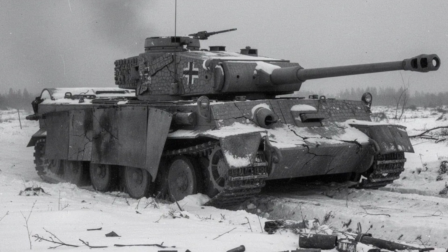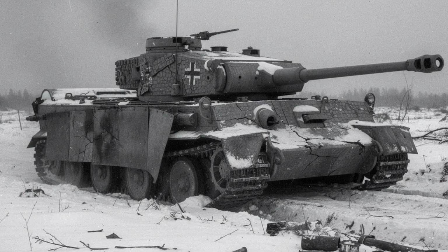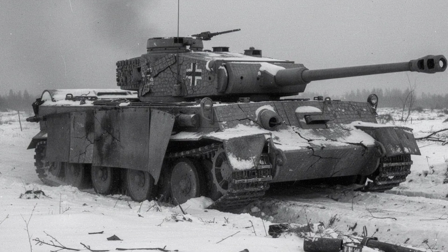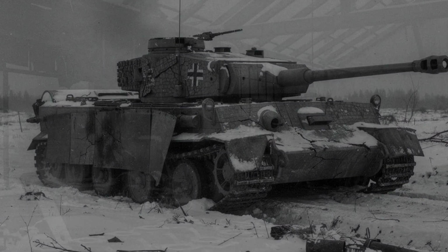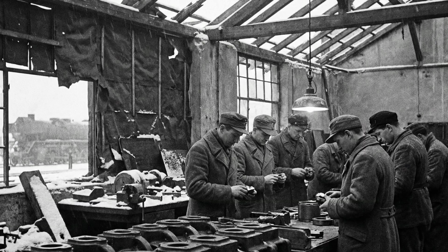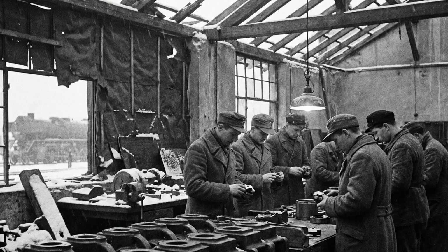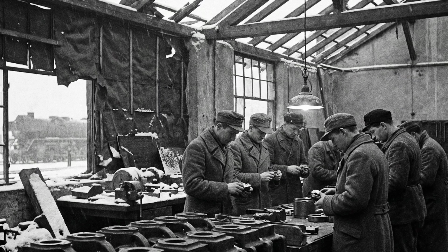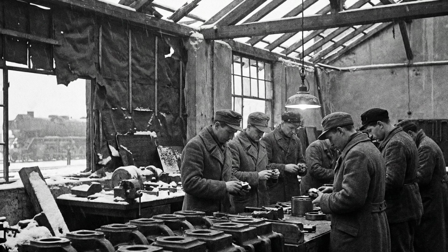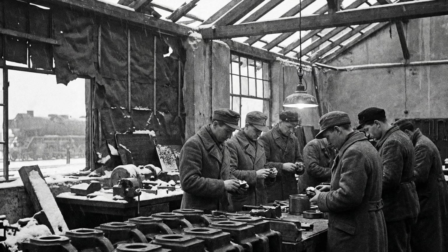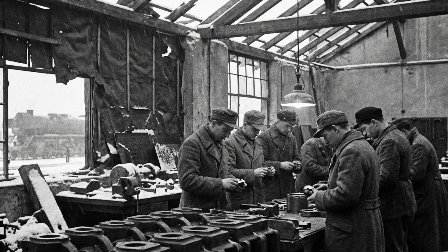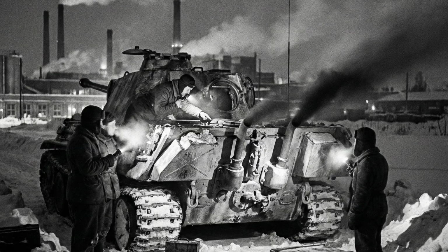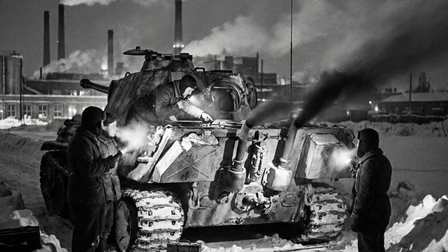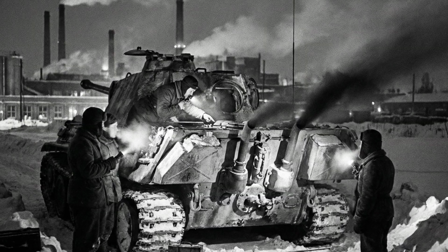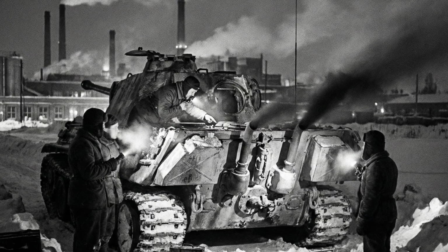Panther complexity. Inside the Panther program, the pressure was constant because the machine itself was complex. The Panther demanded roughly twice the machining hours of the older Panzer IV, about 1,500 hours versus around 800 in early runs. Its armor layout used interlocked plates and long weld seams that saved weight and improved ballistics, but added labor. Its 75mm KwK 42 gun offered long reach and high velocity, but the gun mount and recoil system needed tight tolerances. Each choice improved performance and increased manufacturing difficulty.